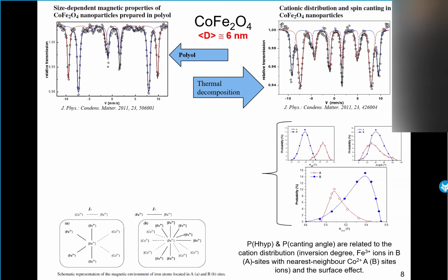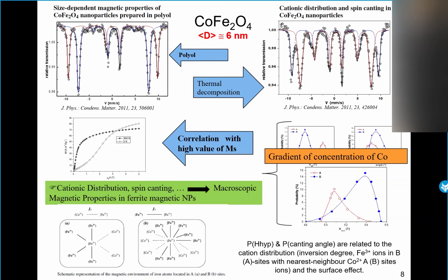And starting from that and from the local magnetic moment obtained from the Mössbauer spectrometry, we arrived to reproduce the high magnetization at saturation observed by SQUID. So the cationic distribution and the correlation between the distribution and the spin canting allow us to understand the macroscopic magnetic properties in this kind of cobalt ferrites.